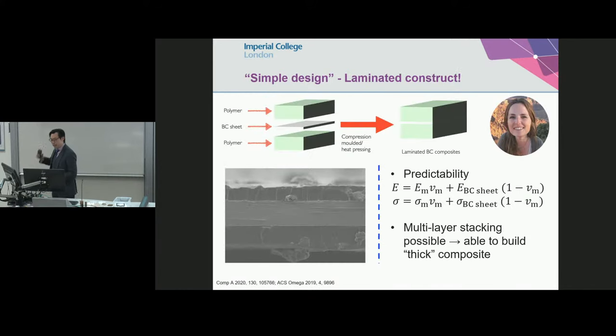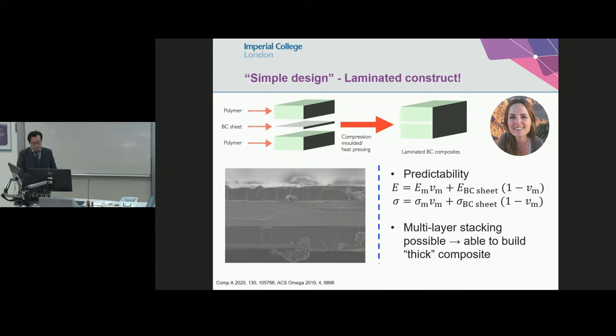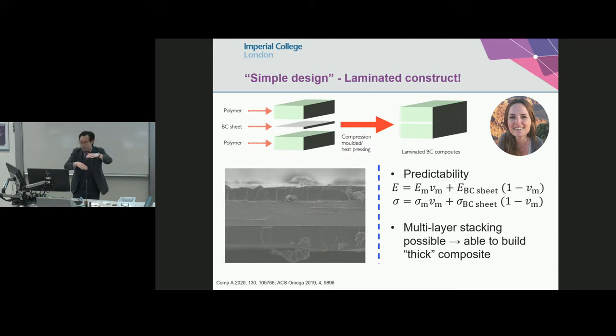Right, so Alba started this work with us. After numerous trials, the idea here is that we come up with a laminated construct. So you would have your polymer, you would have your bacterial cellulose sheet dried, and then another polymer, again, you stack them together, you fuse them together, it should technically work. So architecturally speaking, that's how it looks like at the bottom. Polymer, cellulose, polymer, yeah? And it's predictable, so our funder likes it with that sort of architecture, and you can stack them up quite easily as well. So you can build easily a 5, 10, 20 millimeter thick structure if you really, really want to.